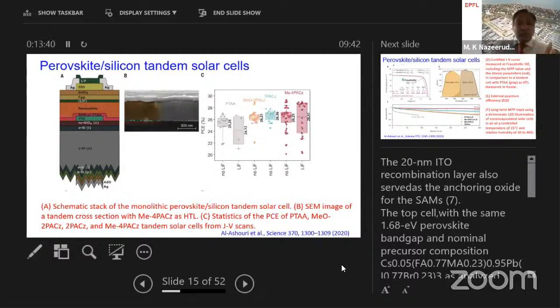If you look at the A panel, it shows a silicon solar cell terminating with the n-layer, and now we have a recombination zone, that's ITO, where the electrons coming from the silicon solar cell recombine with the positive charges coming from the perovskite solar cell. In between we have a hole transporting material, which you will see clearly. It's called SAM, a self-assembled monolayer, or PTAA, which is a polymer. This is a very thin layer of hole transporting material deposited on top of ITO, followed by the perovskite. Now we have an electron transport layer on top of the perovskite, that's tin oxide, followed by anti-reflecting coatings. So this is the cell configuration, which is typically what we call the PIN configuration. This is the cross-sectional image, and the power conversion efficiencies using various hole transporting materials are shown here. If you need more details, please refer to this Science publication from Al-Ashuri.